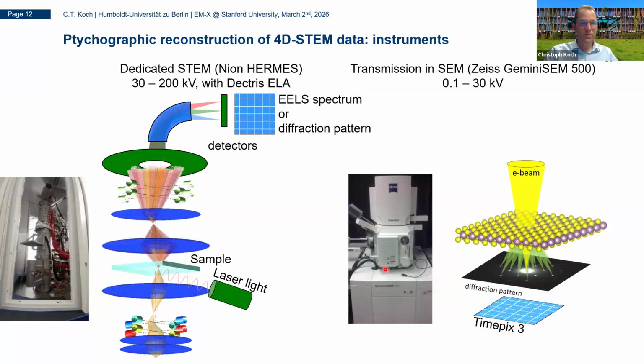And this is what we're going to use for this ptychography work. I will also show you some ptychography done on this very simple instrument here. This is a Zeiss SEM that goes up to 30 kV, has no particular electron optics in it, except it has a field emission source and then a Timepix detector for recording diffraction patterns.